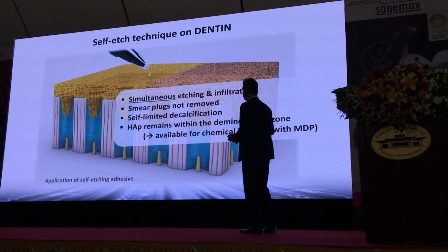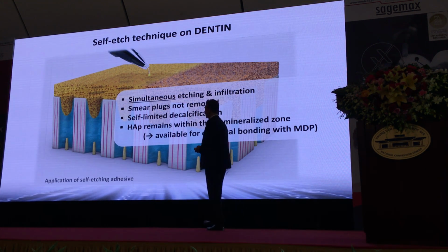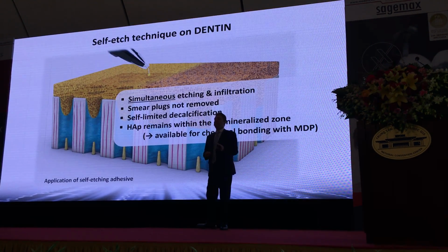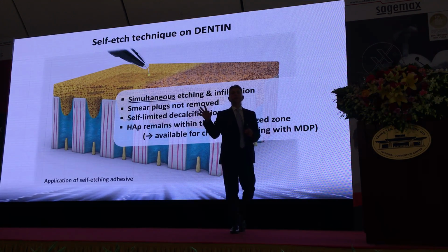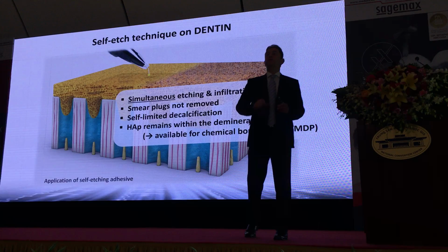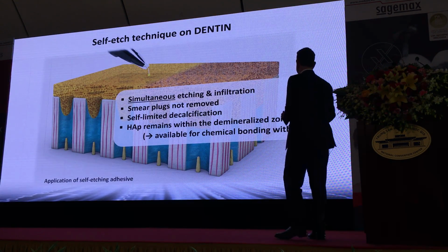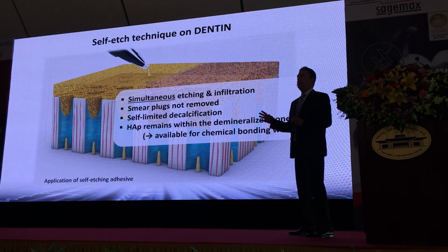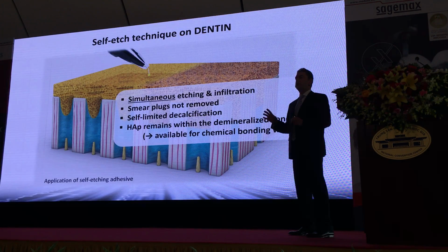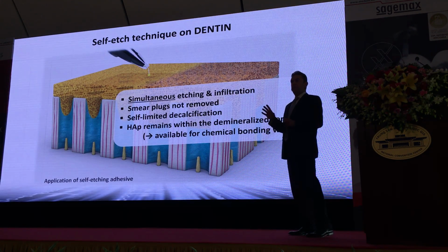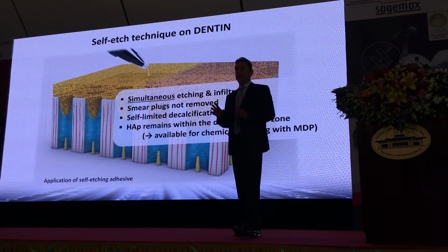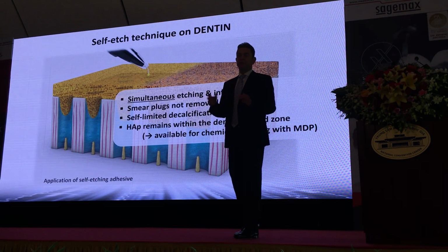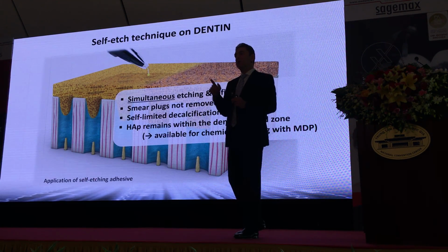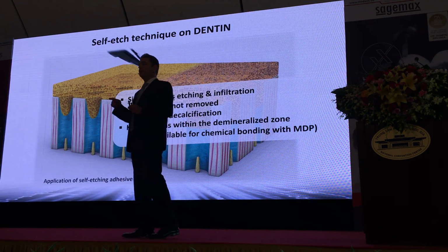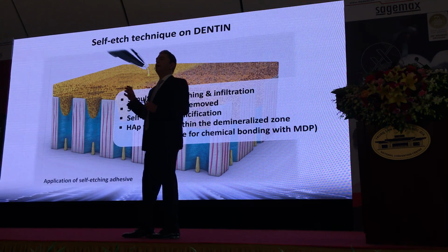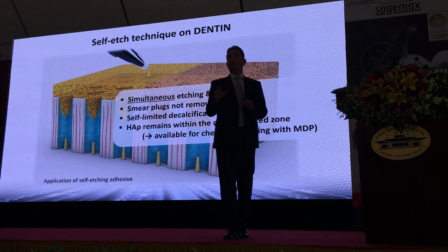Okay. The good thing with Tetric N-Bond Universal is that it contains MDP. MDP is a chemical that not only bonds to zirconia, it also bonds to the tooth very nicely. So now we have MDP, and MDP can chemically connect to hydroxyapatite. Okay? But we should not remove hydroxyapatite from the dentin, for example with phosphoric acid. If we don't etch the dentin with phosphoric acid, we have a better chance to get a chemical bond between MDP and hydroxyapatite.